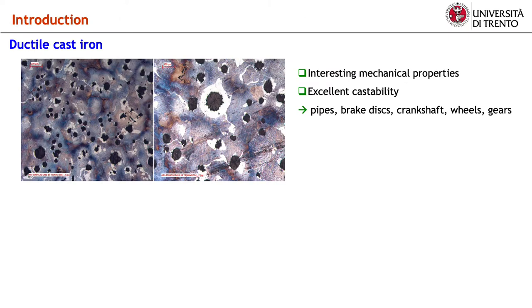Cast iron is an iron alloy with a high carbon content able to considerably reduce the melting temperature and to increase castability. To avoid the precipitation of hard and brittle cementite, silicon is added to the chemical composition to promote the precipitation of carbon in the form of graphite. If high mechanical properties are requested, magnesium and other elements are added to promote the precipitation of spheroidal nodules of graphite. This type of cast iron is denoted as spheroidal, nodular, or ductile cast iron.